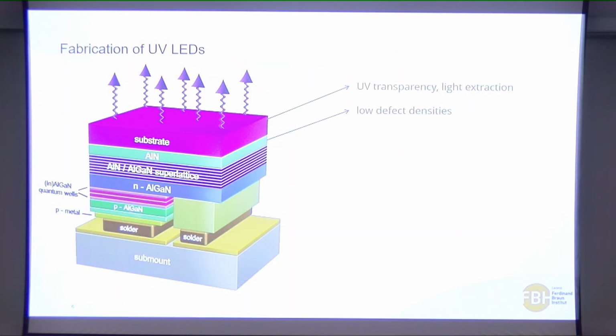Then you have an aluminum nitride layer on the sapphire, and since they have different lattice constants, there is a tendency for defects to be formed at this layer. And therefore you need to reduce these defects, because these defects can then propagate into the active region of the LED and act as traps, so you won't get any light out of these carriers. So you need low defect densities. And then as you go from aluminum nitride to aluminum gallium nitride, you have to make sure again that you have some kind of strain management layers, because you don't want any new defects to be formed while you're continuing to grow. So you have some strain management layers.